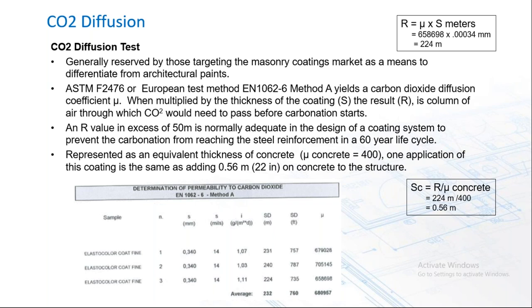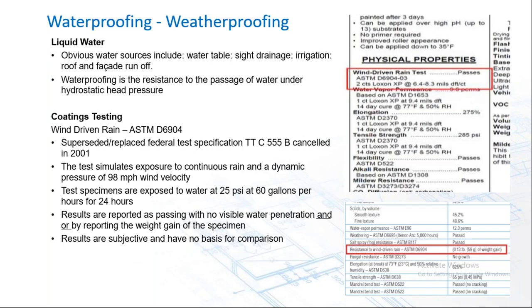To put that in other terms, if you wanted to give your concrete the same protection as that one application of paint or coating, you'd need to apply something in the order of another 22 inches of concrete as a sacrificial layer to provide your structure with the same protection. Waterproofing and weatherproofing, and really the only test that we offer you is a weatherproofing test, and that is the wind-driven rain test. This superseded the Fed Spec 555B back in 2001, but it simulates exposure to continuous rain at a pressure of 98 miles an hour wind velocity. It's typically just a visual inspection, but some manufacturers will go so far as to present you with a differential weight gain before and after the test, as you see there at the bottom.